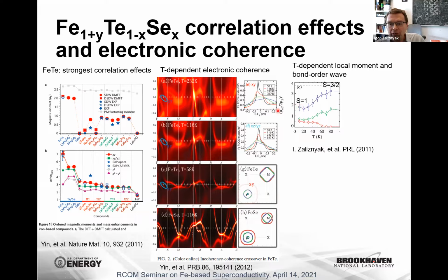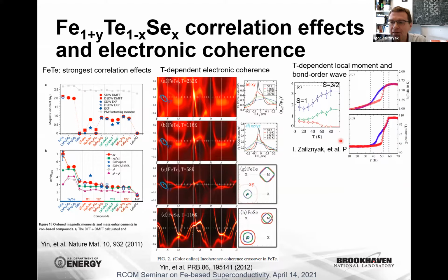So this is in agreement with one electron that gets coherent upon cooling, leaves its local moment localized state and goes into a conduction band. And this was consistent with the measured resistivity, which became more metallic, corresponding to appearance of conduction electrons, and decrease of magnetic susceptibility, illustrating decrease of local moment magnetism.